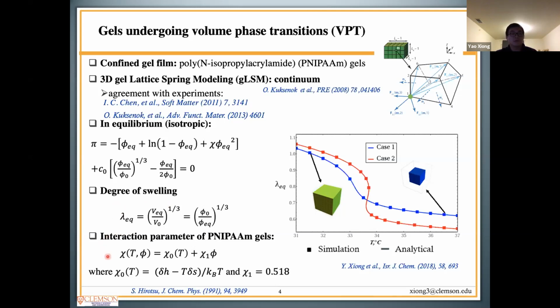Taking the interaction parameters of PNIPAM hydrogel and the other parameters from the experimental study here, our simulation approach has been validated to reproduce the volume phase transition in PNIPAM hydrogels. In this plot, each square represents one independent simulation run. In case 1, gels have relatively higher C0 and higher phi0. Increasing the temperature, those gels shrink and show a continuous volume phase transition. And the gels in red, which have a relatively lower cross-link density and phi0, undergo a discontinuous volume phase transition.